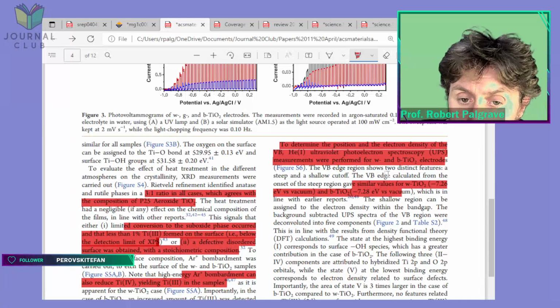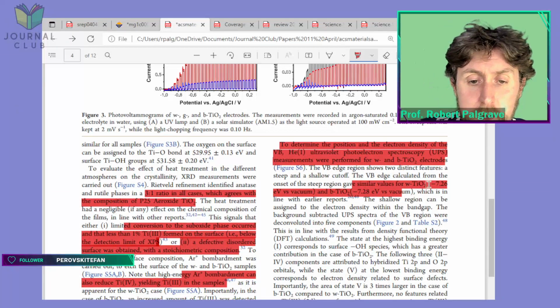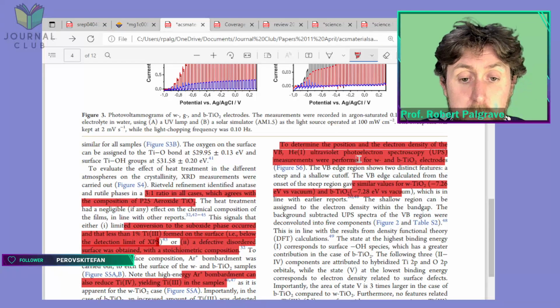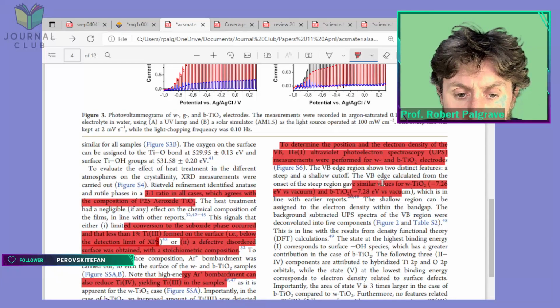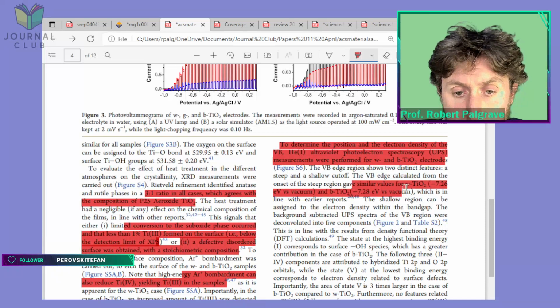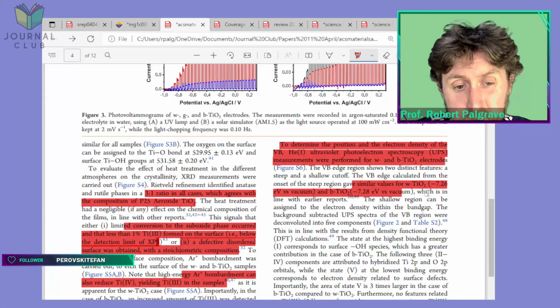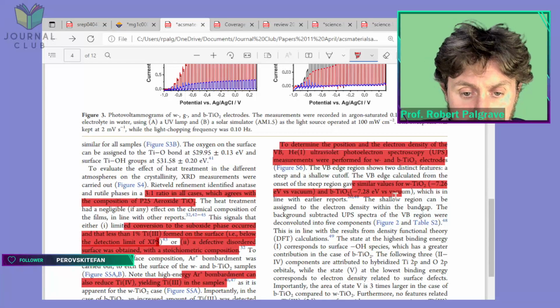So they're talking about the absolute position of the valence band edge, which is to do with the work function. They measure those as being 0.02, so 20 milli-electron volts different, pretty much unchanged, I would say.